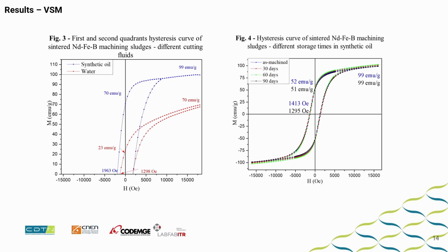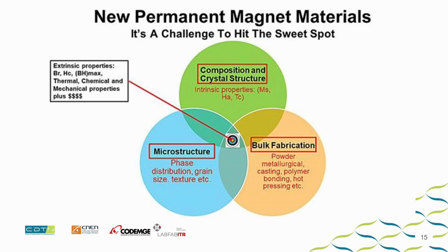And why do we study with this magnetic hysteresis loops? We can find here a decrease, with water, from almost 100 emu per gram to 70. And when we measure with the synthetic fluid, where we keep this permanent magnet stored in oil, over almost 90 days there is no significant change in these parameters. So this is the other study we have done in this CDTN.